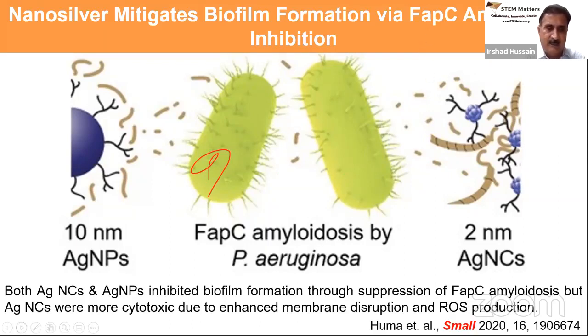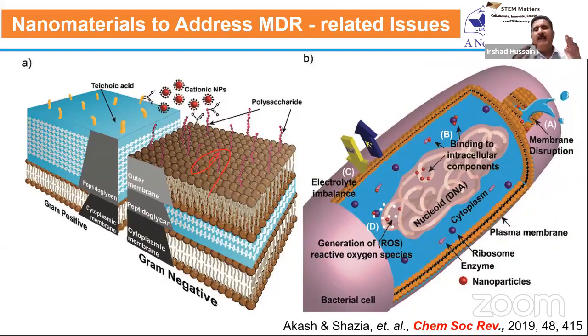in both cases. And more recently, whenever you try to design these nanoparticles to kill bacteria, you really need to take into consideration the surface chemistry of those materials as well. For example, we know that whether it is gram-positive bacteria or gram-negative bacteria, both of these bacteria are negatively charged. So if particles are positively charged, they are definitely more effective in this case. Though negatively charged particles can also kill, they would probably require more concentration of those particles to kill the bacteria. And similarly, by looking at the surface chemistry of this bacteria, their hydrophilicity, hydrophobicity, you can design these particles with controlled hydrophilicity, hydrophobicity, and surface charge so that they can efficiently interact with bacteria.